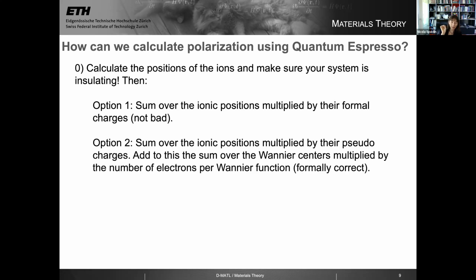If you want to get formally the correct answer, you can do one of two options. The first option, you would first sum over the ionic positions again and multiply by the pseudo charges, the charges on the pseudo potentials. And that gives you the polarization, the dipole moment per unit cell coming from the ions described by the pseudo potentials. Then, of course, you have to add to this the contribution from your valence electrons, and you can calculate that by summing over the centers of the Wannier functions, the Wannier centers, multiplied by however many electrons each Wannier function takes, usually 2 or maybe 1 if it's a magnetic system. And this approach is formally correct. This gives you formally the correct DFT value for the polarization.